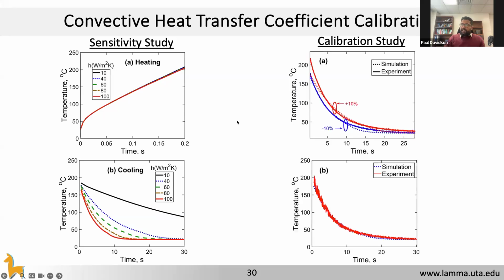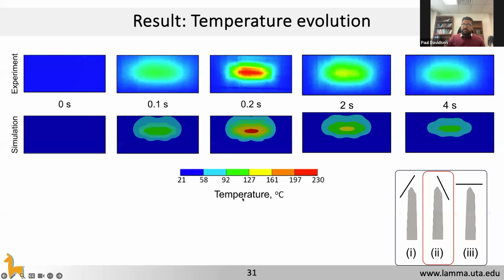And then we did calibration studies and saw how sensitive the calibration was. You can see that even if you increase or decrease by 10%, the temperature readings which we get were fairly close to the experiment. And it is extremely insensitive to any noise in our simulation. So with that confidence, we then did the full temperature evolution for facet 4.